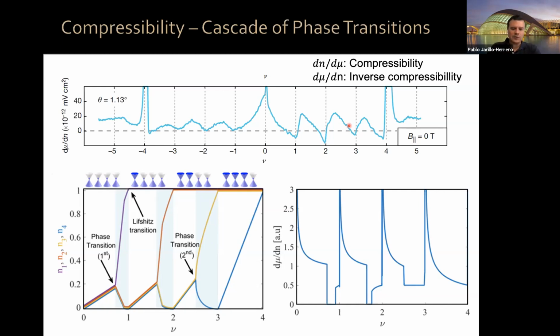But let me just tell you the simplest model, and you will hear from Oscar a more refined model. Remember that we have 4 flavors for electrons in graphene: spin up, spin down, valley K, valley K prime. So initially, let's start from charge neutrality. And this is the population of the 4 flavors as we vary the total filling factor. Initially, all of these flavors get occupied at the same rate. When I add electrons to my system, I'm adding electrons to all of the 4 flavors, starting from charge neutrality.